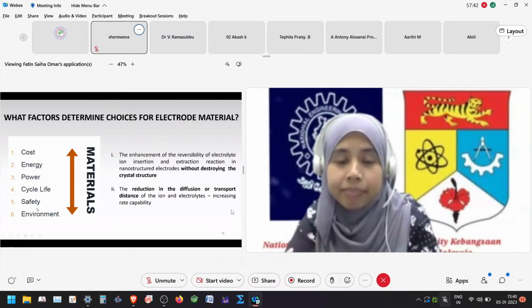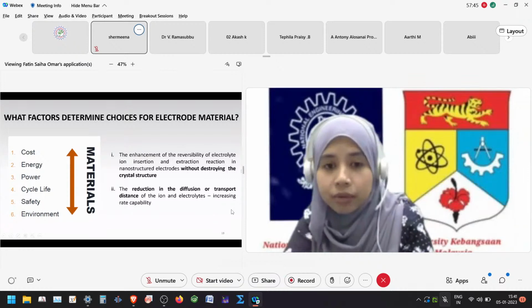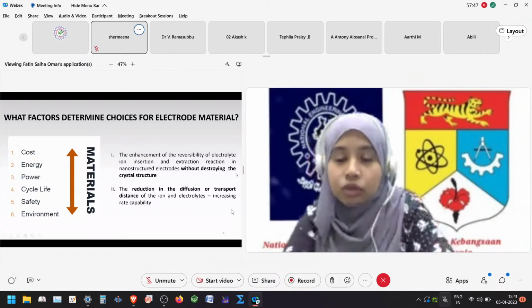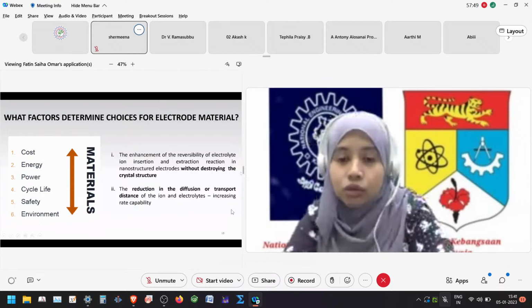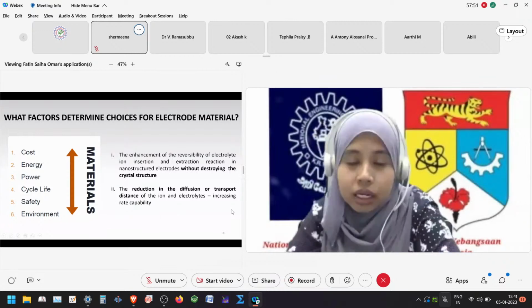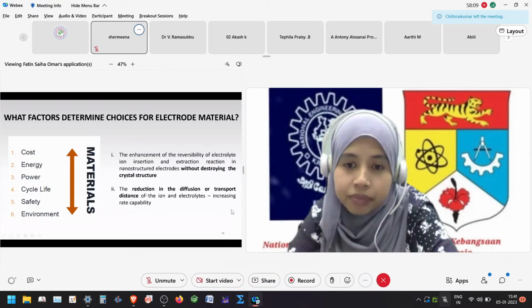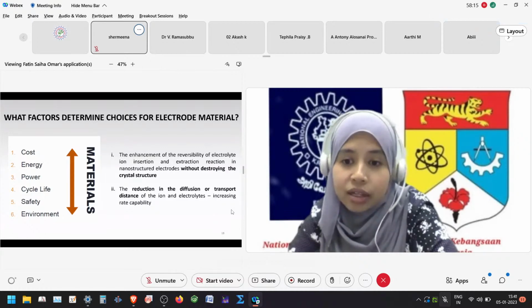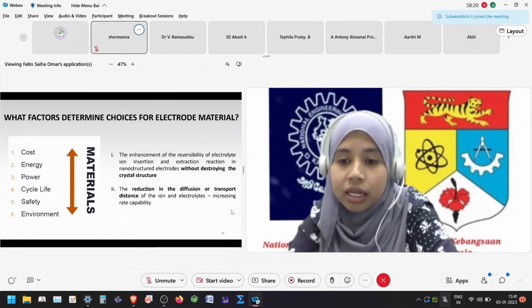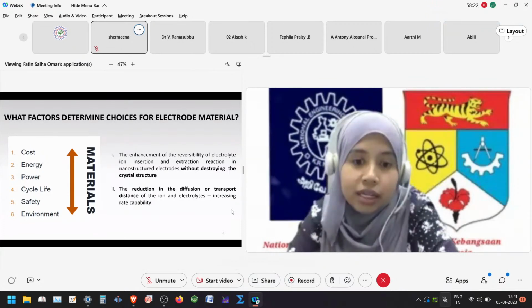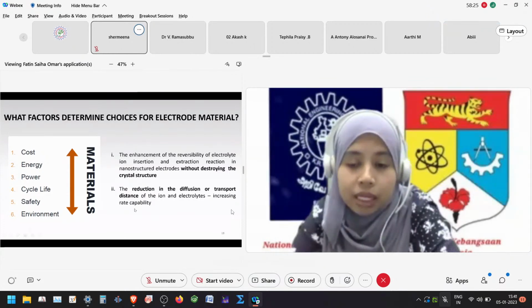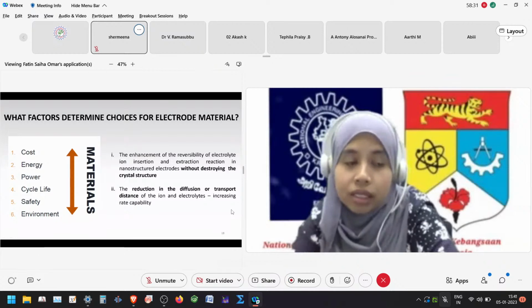And microscopically, we want the material to be very stable during the repetitive charging and discharging, with short diffusion channels for the movement of the electrolyte ions, because short diffusion channels for the electrolyte ions can influence the rate capability of the electrode. So rate capability means the ability of the electrode to maintain its capacitance from low current applied to higher current applied.